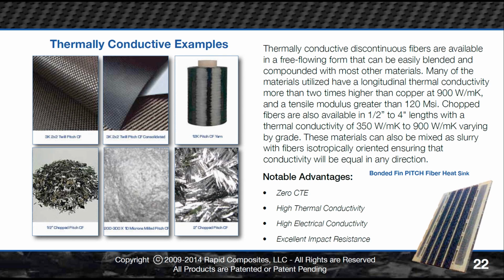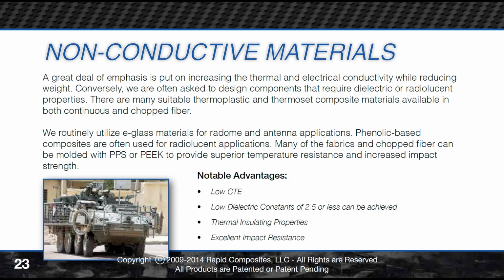Pitch fiber will do about 4x better than that aluminum will. So it's quite a bit more efficient. Now we work with a lot of conductive materials and superconductive materials, as you can see with pitch fiber, and then also we co-laminate metals in ways that are quite unique, where you can actually solder to the structures, as I showed you with the expanded metal.